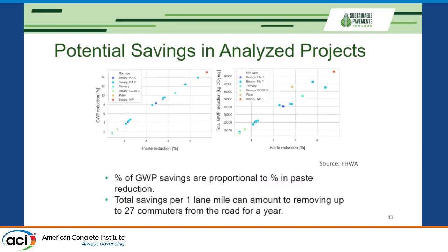In this slide, I'm investigating potential savings in our analyzed projects. If you remember, I am analyzing my 17 mixes that had potential for paste reduction between 1 and around 5% because they were over-designed. They had higher content of paste than 25%. And we can see that the more paste we reduce, obviously, more GHG reduction in percentages we will have. So the worse off you start, the more improvement potential you have, and the improvement potential by doing this can be up to 15% saving just by mix design optimization.